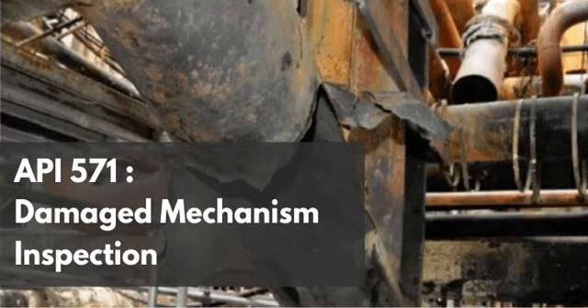Oh. You solve the carbonate cracking vulnerability, but you create a pipe that might shatter under a low-temperature pressure surge because you baked all the toughness out of it. Exactly. That 25-degree window is the absolute metallurgical sweet spot. It provides enough thermal energy to neutralize the mechanical driving force of the residual stress, effectively disarming the ACSCC mechanism while remaining cool enough to preserve the required structural integrity and impact toughness of the steel.